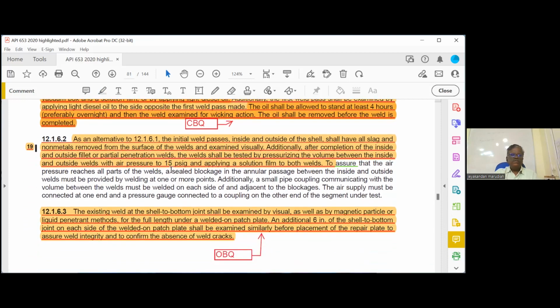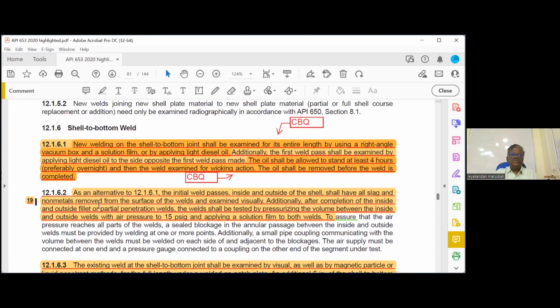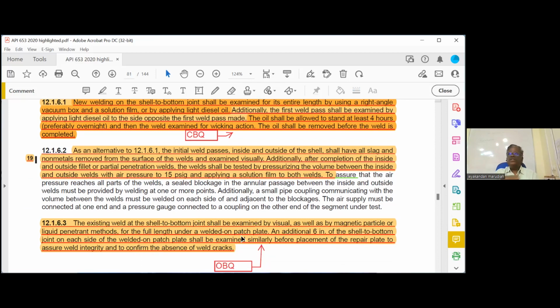Then these are not important. Then 12.1.6.3. The existing weld at the shell to bottom shall be examined visually as well. These are talking about the repair and reconstruction. Magnetic particle full length under the welded-on patch plate. Joints on each side shall be examined similarly before placement of repair plate. See, the existing weld at the shell to bottom joint shall be examined visually as well as by magnetic particle or liquid penetrant. This is talking about the shell to bottom weld. For the full length under the welded-on patch plate, if you are making any welded-on patch plate near the shell to bottom, that area, the shell to bottom weld, you have to do MT. In addition, 6 inch of the shell to bottom on each side of the patch weld shall be examined similarly. Highlight this. Open book question.